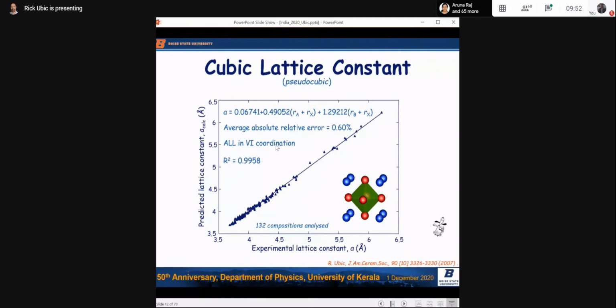it's difficult in some cases to find 12-fold coordination values, but more importantly, they're not known to the same precision as the 6-fold. If you look at all the cations on the Shannon tables, virtually everything exists in 6-fold, and then you often get other coordinations as well, because the radius varies with coordination, in case you didn't know that. That's important. So the 12-folds are just not known to the same exactness as the 6-folds. So we just use the 6-fold numbers and it works. That's all our model is saying, right? It works. Not saying it's right, but it works. Okay.